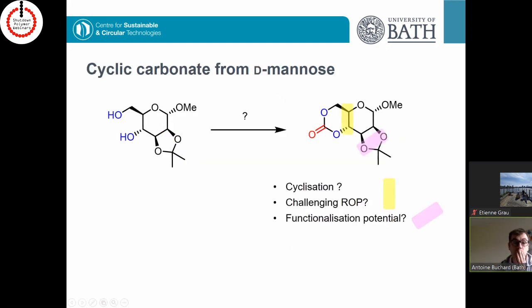So our first target was, can we make this type of cyclic carbonate from mannose? And the reason why we wanted to explore mannose was because that's a fairly abundant sugar that you can get from a variety of sources, including some algae, some coffee grounds, etc. And we thought that this would be the perfect monomer because, like glucose, this would produce a quite strained 6-member cyclic carbonate ring. And also that would have this isopropylidene function here that would open the way to further functionalization. So that was our initial idea and our initial target.